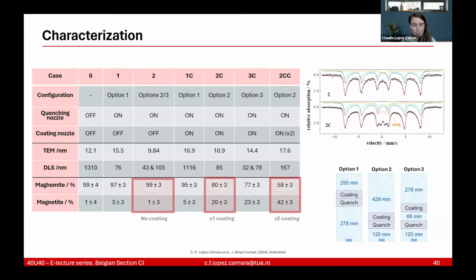And I want to focus the results on case 2, which was the option that we had the quench and coating together and closer to the nozzle. So when there is only quenching, which is case 2, the magnetite phase is 1%. But when we have coating, the magnetite phase is 20%. And when we have double the coating, the magnetite phase is even double, it's 42%, which basically tells us that coating does help us on getting more magnetite phase, and increasing the coating even increases more the magnetite phase. So that was actually a very important result that we got.